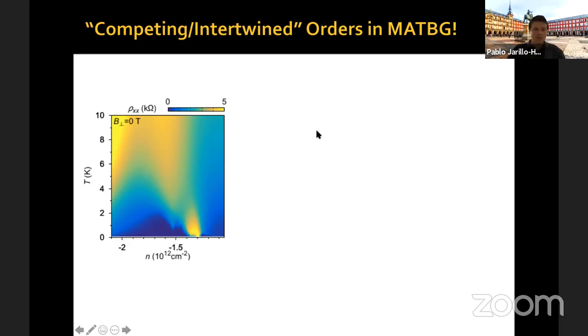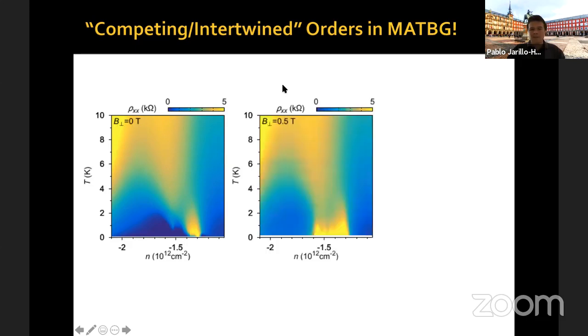So these are the data at zero magnetic field. If you now apply a finite magnetic field, we saw that this wedge leads into an insulating region at zero temperature, which is connected through a set of insulating states to the correlated insulating state at 2 holes per moiré unit cell.